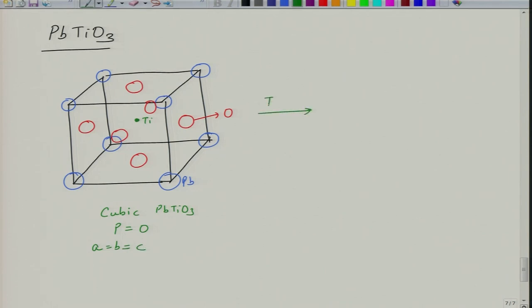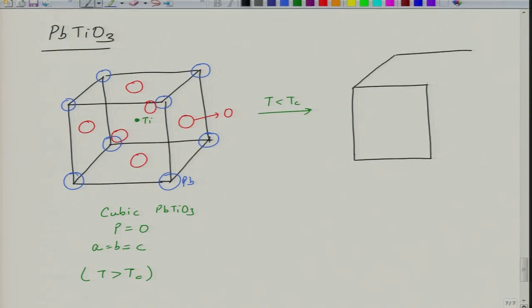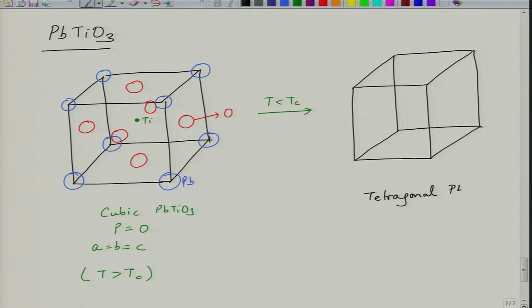This is at T greater than TC. As you cool it below TC, when T is lower than TC, this will transform into a tetragonal structure. So what will happen is that the a and b parameters will be different now. So there will be a lattice distortion leading to the formation of a tetragonal structure where a = b is not equal to c, and P is not equal to 0.